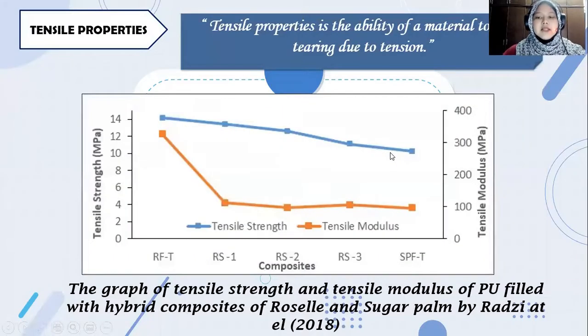Next, on tensile properties. Tensile properties is the ability of a material to resist tearing due to tension. This graph shows the tensile strength and tensile modulus of polyurethane filled with hybrid composite of roselle and sugar palm by Radzi et al. in 2018. They have slightly decreasing tensile properties when sugar palm fiber is added. This graph shows that not all fibers are suitable for hybrid composite and may have weak adhesion between the particles of the specimen.